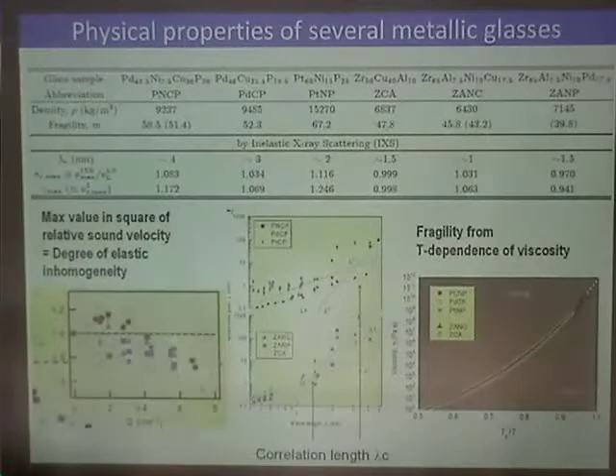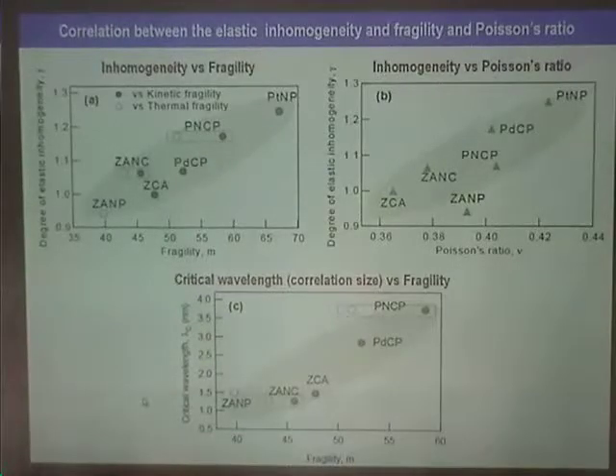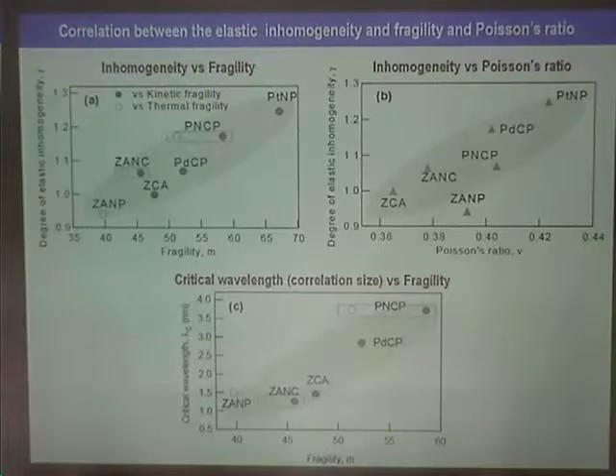So we have summarized the relations between some properties. This is the degree of the elastic inhomogeneity and the fragility. This is the degree of the elastic inhomogeneity and Poisson ratio. And this is the tendency of the critical wavelength and fragility. So we see some correlation between these three properties.